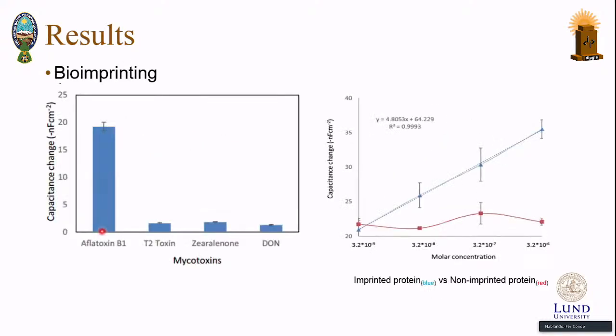Another way to have our biorecognition element is bioimprinting. We have seen that when using bioimprinting, we need to have one molecule that is the bioimprinted protein when the target analyte is set up with the aflatoxin, with the imprinted protein and the non-imprinted protein. And in this figure, we can see that there is some kind of non-specific interaction with the non-imprinted polymer. We realized the measurement of aflatoxin B1 in a certain concentration, also with the same concentration for T2 toxin, zearalenone, and DON, and we have seen that there is some unspecific interaction, but it's not high compared with the main measurement that we are realizing for aflatoxin.